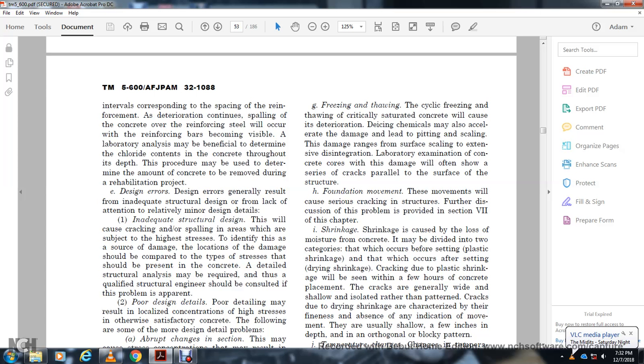Cracking due to plastic shrinkage will be seen within the first few hours of concrete placement. The cracks are generally wide and shallow, isolated rather than in a pattern. Cracks due to drying shrinkage are characterized by tightness and fineness and the absence of any indication of movement. They are usually shallow, a few inches in depth, in an orthogonal or block pattern.